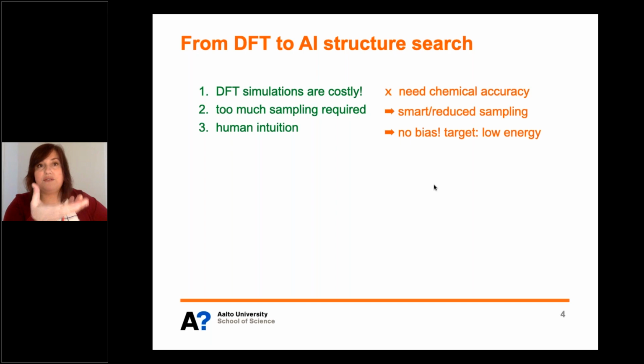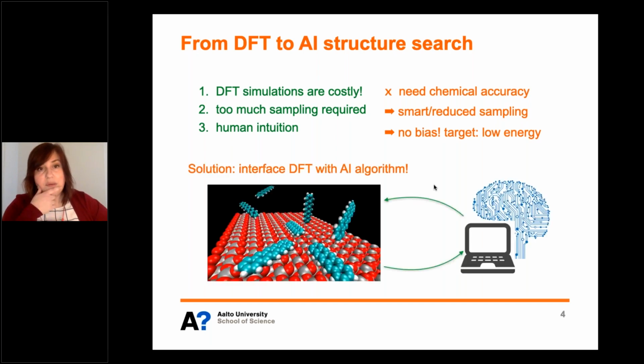So we thought it would be great to use AI to do some kind of AI structure search to solve these problems. Now, there's not much we can do about DFT. We definitely need chemical accuracy. We have to keep that. But maybe we can do some kind of smart reduced sampling to solve the sampling problem. And as for intuition, we really don't want to do that. So ideally, the machine would just look at energies and tell us what the low energy structures are. The solution we came up with is to interface our DFT codes with some kind of AI algorithm and leave it to the machine to choose relevant molecule-on-surface configurations, learn about their energies, and then from there predict which ones are the most stable.